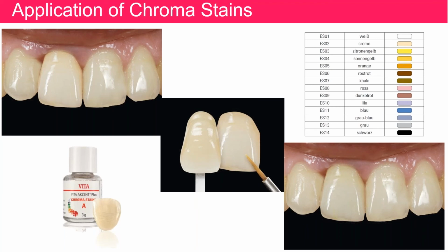This material is used for all of our zirconia, all of our feldspathic porcelains, anything ceramic-wise that you mill, Suprinity, and so forth. Those are all used for this to help create it and make it a little bit more chroma. And I can't stress this enough: before you start adding stains on these translucent modern materials, including zirconia now, because we have a zirconia called YZ Solutions XT that's almost 50% translucent, you really have to know what that underlying prep color is. So make sure you're always using this like a dye.